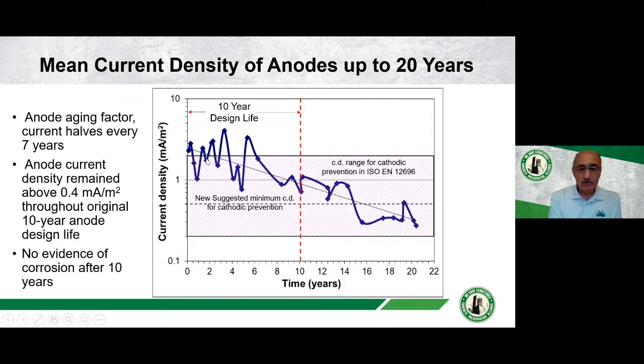So looking at the current output over time, if you plot it on a logarithmic scale, this is the mean current density of all the anodes, so it's current density by steel reinforcement. We can loosely put a straight line through it, and the fact that it's a straight line on a logarithmic scale tells us that the current is halving every fixed time scale. In this particular case, it's every 7 years. So if that's your initial current, at 7 years, it's half that. Another 7 years, at 14, it's half again. And at 21 years, it's halved again. So it gave us an understanding of the performance of the anode set. We know how long it can last, and we know how the current is diminishing with time.